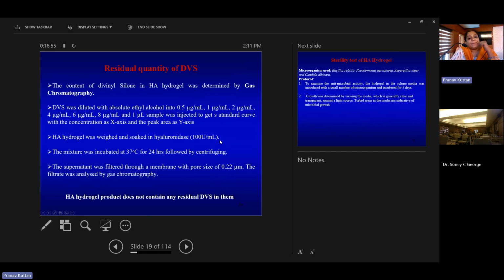Then after the development, we wanted to see, we want to give it into the body. So it is very important that we find out whether some residual quantity of divinyl sulfone, that is the crosslinker, is present in the hydrogel or not. So what we did was, we determined the amount of divinyl sulfone using gas chromatography. So divinyl sulfone was diluted with absolute ethyl alcohol at different concentration, and a calibration plot was made.